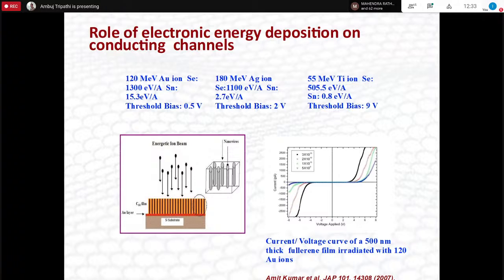And if you are saying that it is related to the electronic energy loss, these are the type of experiments you do. As you can see, we have taken 3 beams: 120 MeV gold, 180 MeV silver, and 55 MeV titanium. What varies, in the next line, you see the electronic energy loss value, which is around 1300 in the first case, 1100 in the second case, and 500 in the third case. So you vary the electronic energy loss, and if you are saying the conductivity is because of this Se value, then it should vary with that. So as you can see, the threshold from where the current starts, this black, red, green, and this blue curve.